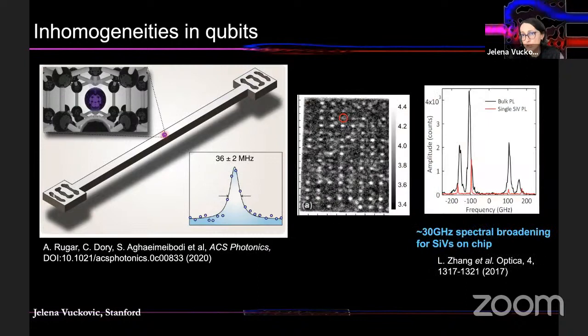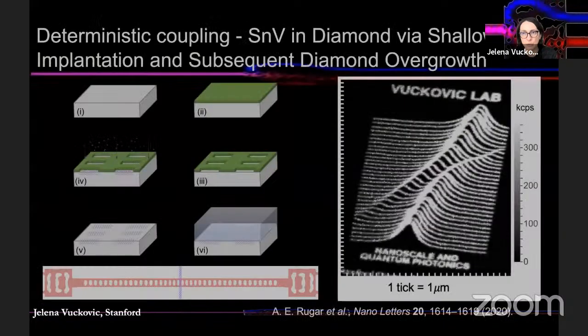And the main issue is inhomogeneities in these systems. A lot of these inhomogeneities come from the fact that you have to use very sophisticated methods to build these systems. They are so much smaller, and you have to really control individual atoms in a solid state structure, and that's really not a trivial process. So you encounter spatial inhomogeneities, meaning that it's difficult to insert these atoms at the desired positions with perfect yield, and also spectral inhomogeneities, which come from the fact that these atoms are not in vacuum, like neutral atoms in atomic cavity QED, or ions. Instead, they're in solid state environments, and any imperfection would lead to shifts in the transitions, which for us in the best case scenario are on the order of 30 gigahertz. So we spent a lot of time developing methods for both spectral tuning and compensation of spatial inhomogeneities in order to be able to build scalable systems.